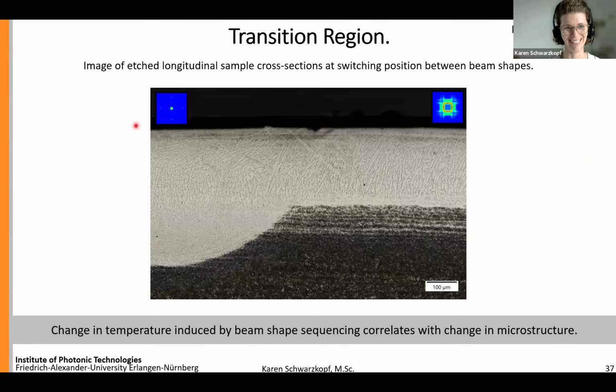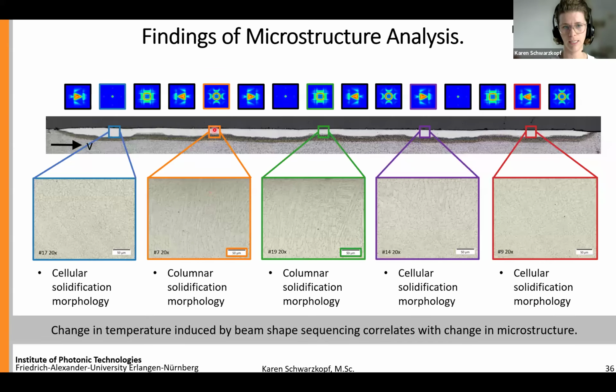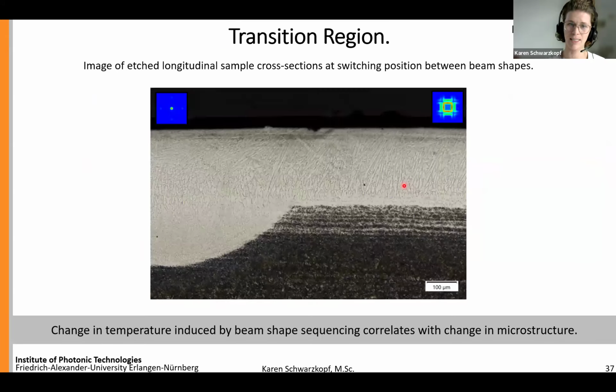Oh, sorry, no. I forgot that I also wanted to share this image with you, where we can basically see the transition region, because if I'm stepping back, these regions here were imaged in the center within one beam shape. But what is also interesting to see, because we never had that before, is what is happening in the transition between two beam shapes. And this again emphasizes that we are able to really transfer from a cellular-like structure to a rather columnar structure only by changing our beam shape here. All right, now let's jump back to the hardness measurement again.